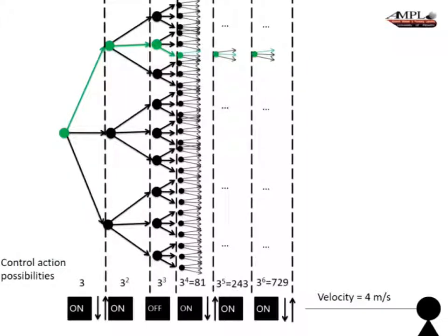The most efficient way to do that, we found, was using a branch and bound technique. So this is the starting point, and with the starting point you might have a bank that may be on or off, and then this one might be involving the side sprays as well. So the side spray is on and the bank is on. This one has the bank on but the side spray is off, and this is both off, for example. And so you do your calculation at that point and you see how far you are along the path through the CCT diagram. And then once you pick the one that's closest to where you want to go, you then go to the next bank and you repeat the same process, and you march along until you reach the very end.